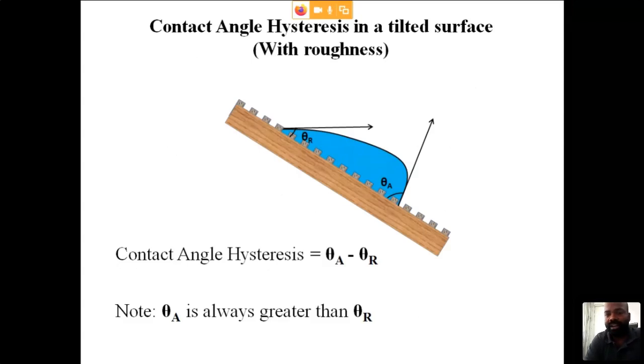If you want to make a super hydrophobic surface, then the contact angle has to be higher than 150 degree. At the same time, the contact angle hysteresis should be very, very low. It should be less than 5 degree or 10 degree. Only in that case the droplet will actually roll.